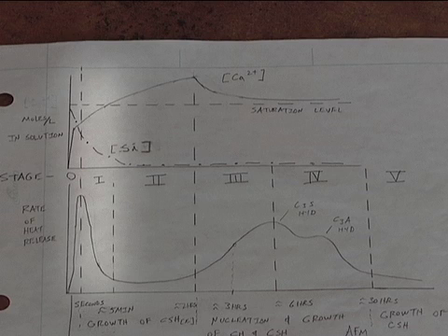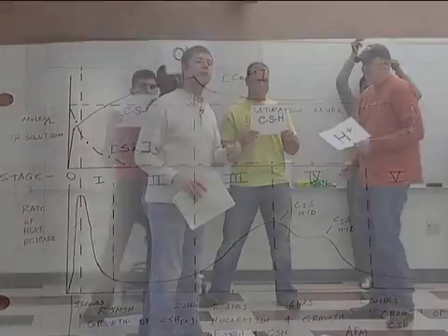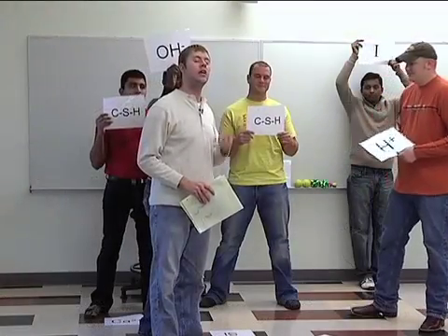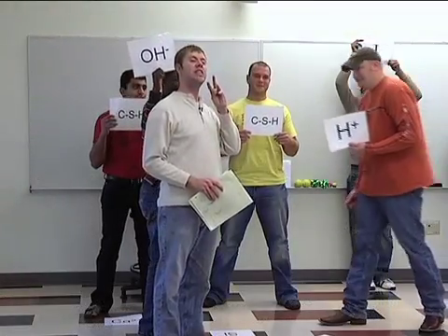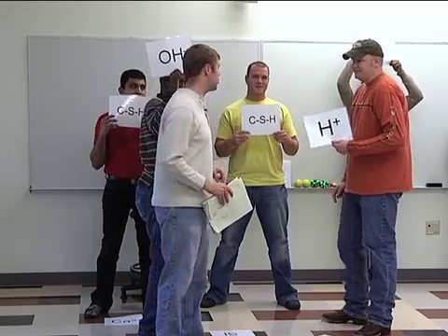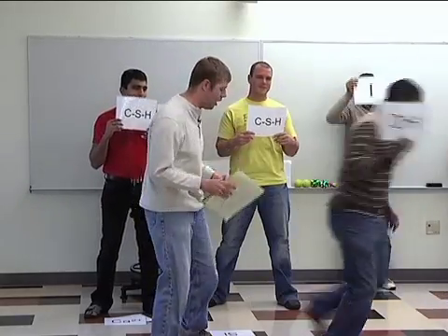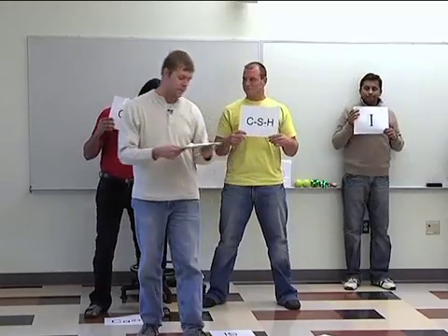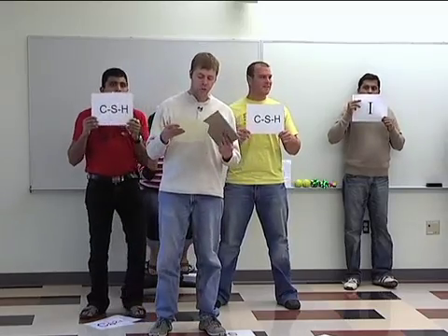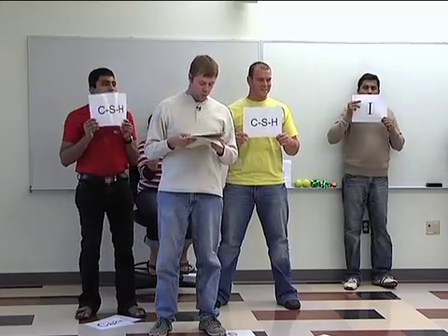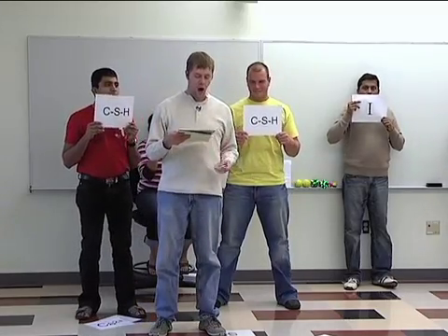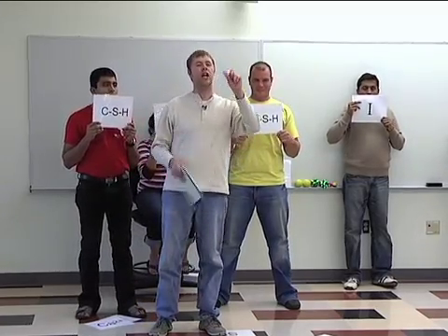There are a few water molecules that make it through. Once they do, they get in and they form a little bit of CSH but it doesn't happen very regularly. It's likely this CSH is a very, very dense microstructure — very hard for water to get in. So we're in stage one, we're slowing down, our cement grain is changing.